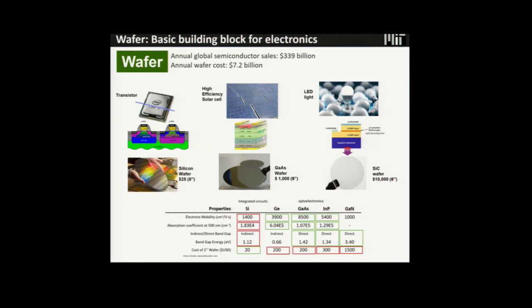It's so expensive. And LED is also an interesting case because we cannot use silicon. There's no choice but to use other direct band gap materials to emit light. The most popular material so far is gallium nitride. In order to grow a high performance gallium nitride LED, of course, you need a super expensive wafer, which is typically silicon carbide. Silicon carbide, 6-inch, $10,000, and you have to beg the vendor to sell this wafer. It's rare. You can easily buy a 4-inch wafer, and that is still about $3,000 to $4,000. For an assistant professor like me, it's so expensive.